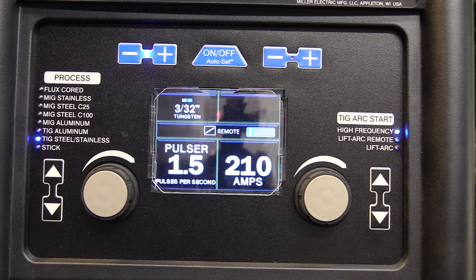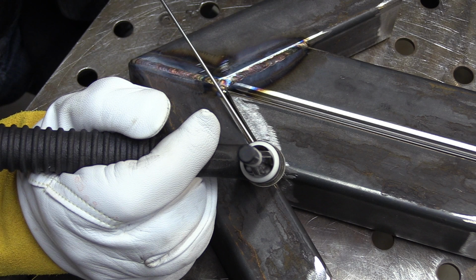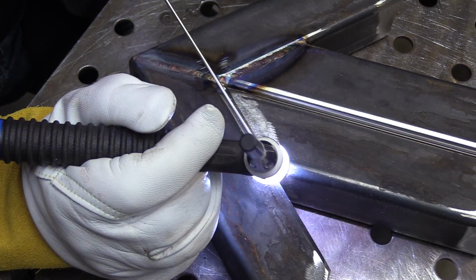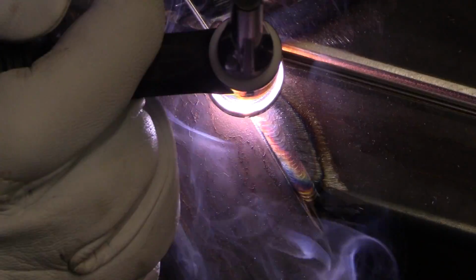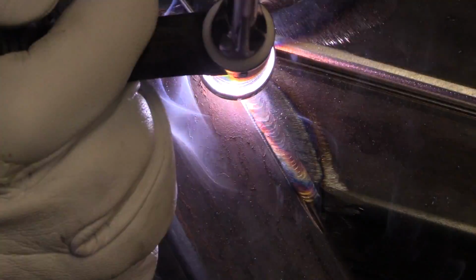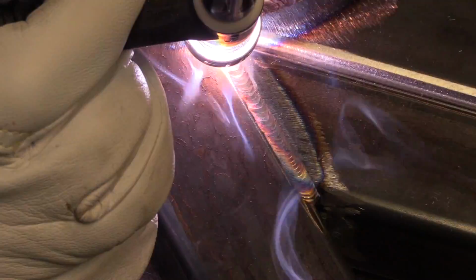So in this case, it's carbon steel. I just don't want to pull in all those oxides into the puddle and make it not flow good. So I set the pulses per second to 1.5 pulses per second. Whenever you use pulse, you need more amperage. So I got the amperage maxed out to 210 amps here. And at times, not for this weld, but at times I would be using all of that. But this one I'm maybe 1/2 to 3/4 foot pedal. So again, you can use pulse to your advantage and control your heat and not penetrate all the way through something. And in this case, you can see that bead is going a lot smoother, a lot more regular, a lot more even, because I'm not pulling in oxides from the backside.